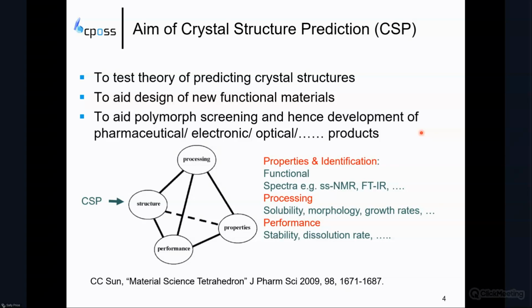This evolved initially for curiosity to test theories for predicting crystal structures, but rapidly became recruited as an idea that it should be able to aid the design of new functional materials. We got our first funding for developing the modelling from an organic nonlinear optical initiative, because they'd synthesized so many molecules with high nonlinear optical properties that then crystallized in a centrosymmetric and then inactive crystal structure.